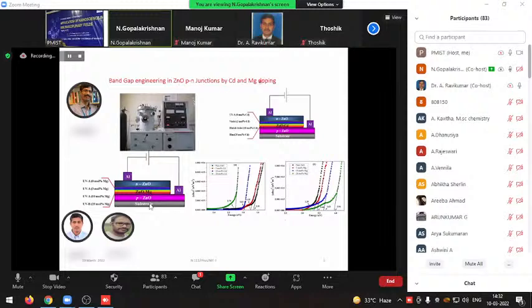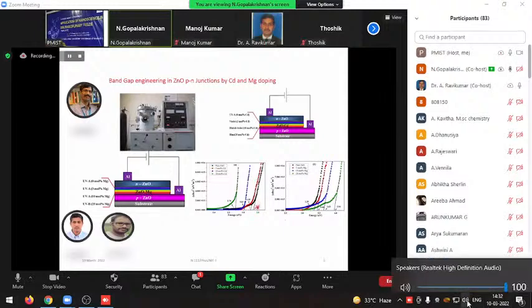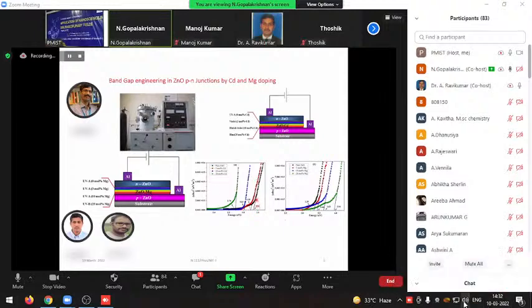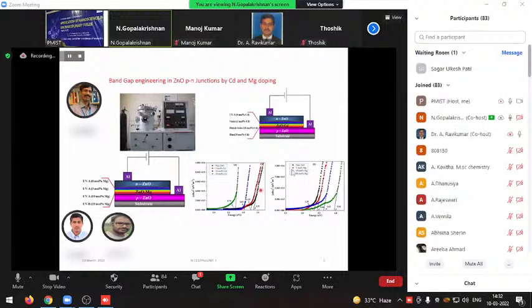Upon Mg doping of zinc oxide, the band gap increases. Look at this, I have given the Tauc plot here. First, in the case of the cadmium zinc oxide film, zinc oxide mainly has a band gap of 3.35 electron volt. Upon doping with cadmium at different concentrations, the band gap decreases. We can tune the band gap down to 2.7 electron volt.